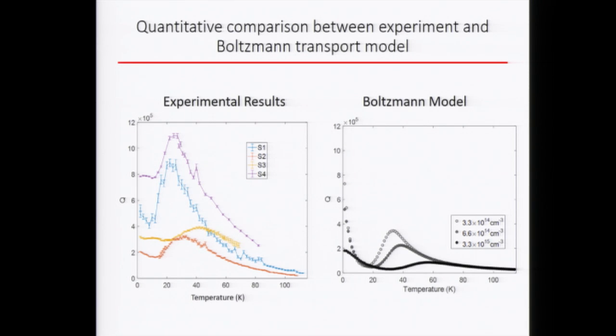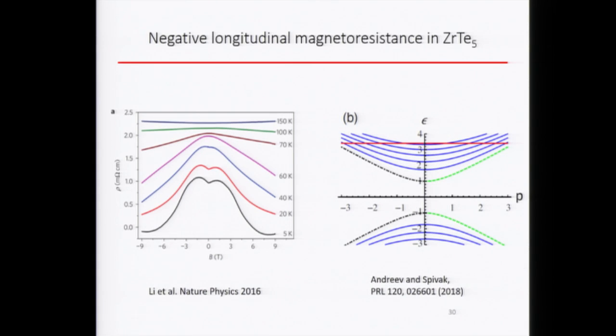Okay, so this is all zero field measurements. Remember that there is also the chiral anomaly associated with the Dirac semimetal. People did observe chiral anomaly, or longitudinal negative magnetoresistance, in this set of crystals. And since this material is likely gapped, how does it happen? I won't go into the detailed theory, but there's a theory work done by my colleagues Andreev and Spivak. They basically prove that in a semi-classical regime, the same kind of phenomenon will still apply, and you'll still observe the same kind of negative longitudinal magnetoresistance, provided that the Fermi energy is large compared to the gap.